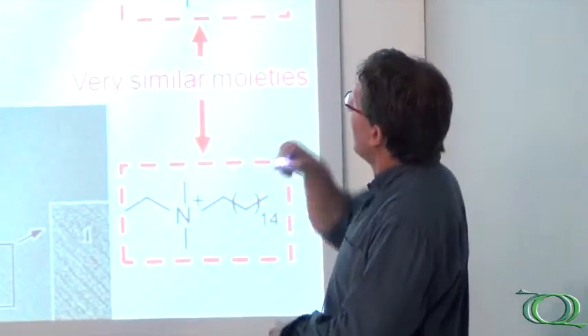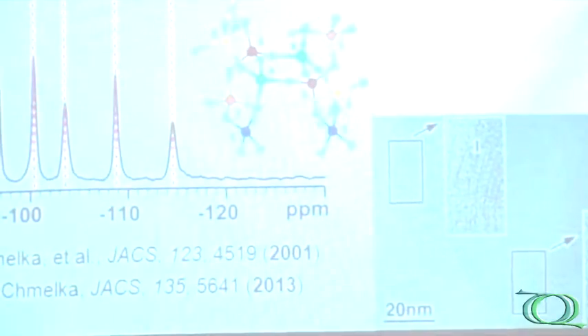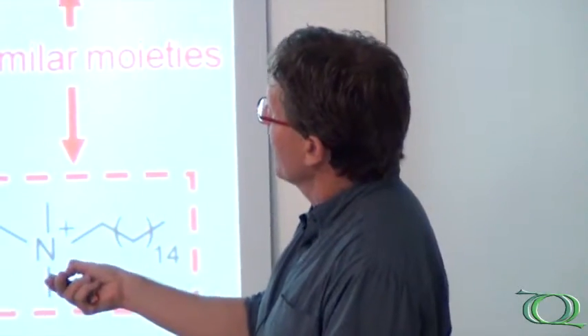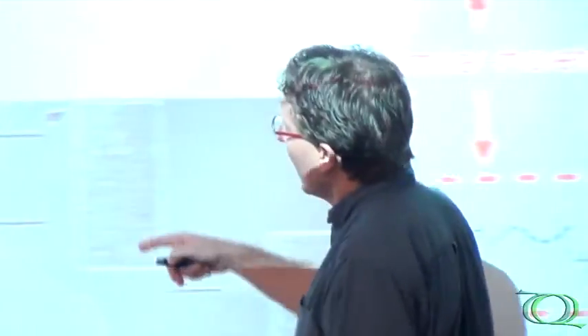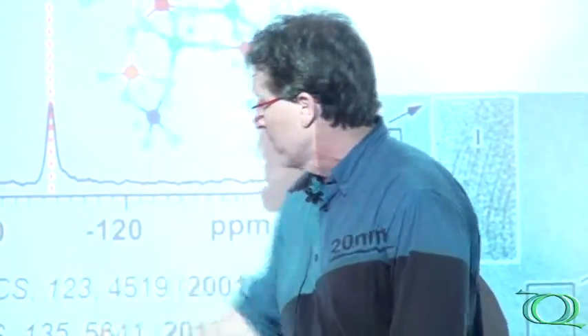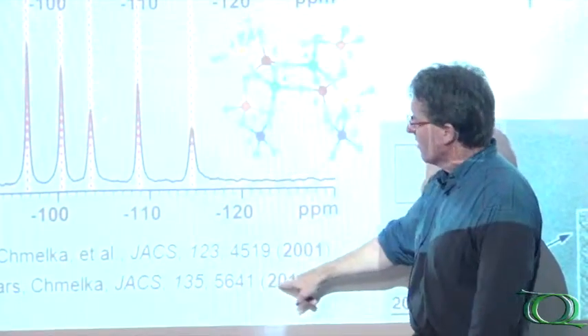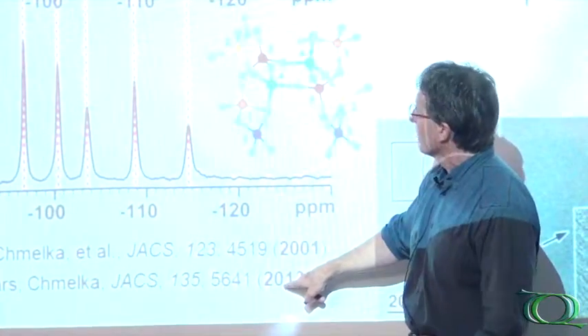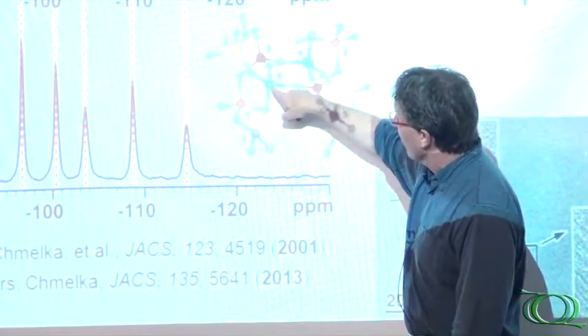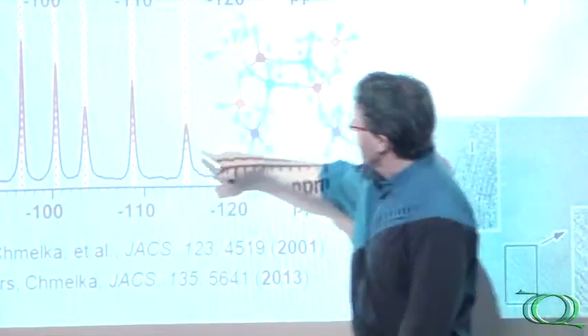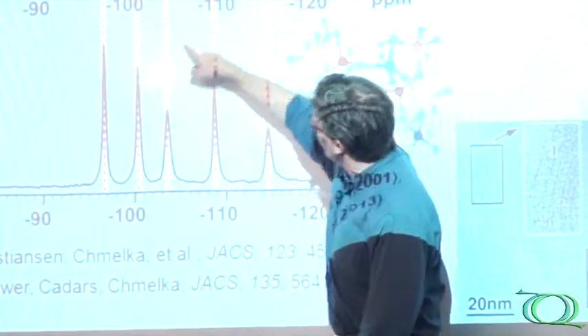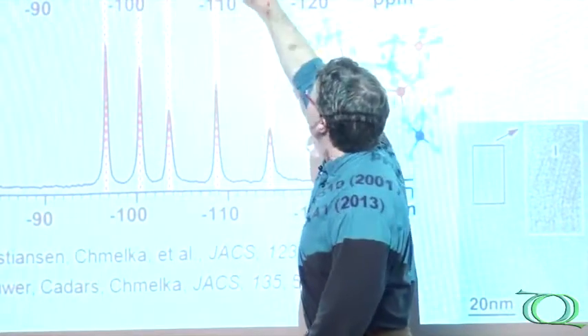And to convince you of that, here's the material that I just discussed. There's five peaks after eight days and here's the same spectrum that's taken from the first paper in 2001, we just had this published in JACS last month which outlines the structure of this framework. And this material, if you look at the signals, they line up exactly underneath the peaks of these guys.